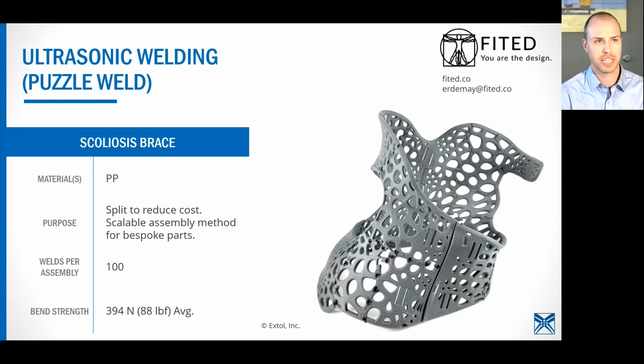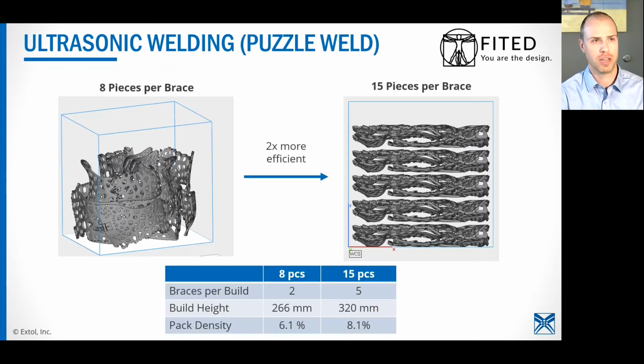And then we also need a scalable assembly method, because this is something that is launching to production, and using adhesives at this scale is not something that is too fun for any of you that have experienced it. So we ended up with about 100 welds per assembly, and we'll take a look at some of the bend strength, but the joint strength was almost 400 newtons for each joint that we had.